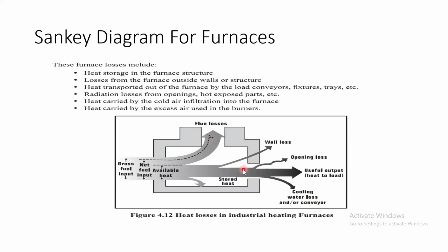So this is a major heat loss going to flue gases. Another heat loss is the loss in the walls. The wall becomes heated, and you find it very hot when you walk across this area because of the wall losses. Opening loss is also very well known to you, because while loading and unloading there is a gap in the furnace, and that gap directly exposes the 1500 degree centigrade melting temperature to the atmosphere at say 30 degrees. Because of this a huge loss occurs, and that is called the opening loss.